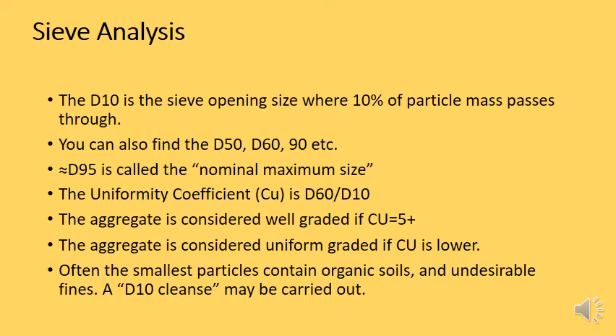Now, if you have a well-graded aggregate but you don't want it to have high porosity, one of the very simple things you can do is called the D10 cleanse. Basically you take the 10% of the aggregate which is the smallest, so you put it through a big sieve, and the smallest 10%, you throw it away. You do away with it, and basically you're cleaning the aggregate of the organic soils and the clays and the silts and all of these really undesirable particles which have high porosity. Then you're just left with sand and crushed rock, which is much more stable and has much less reactivity with water. That's called the D10 cleanse.